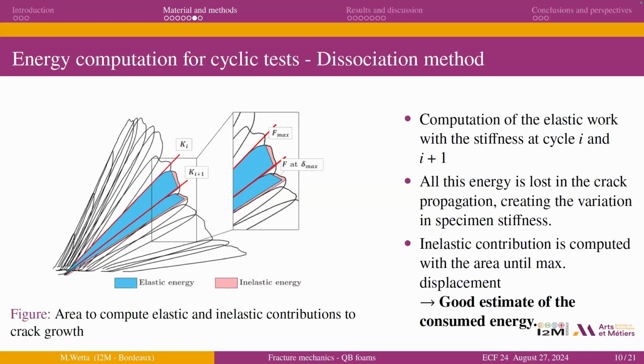To do that, we dissociate the blue and the red area. The blue is considered to be the elastic energy, which is estimated between two different stiffnesses, because when you reload the crack, you have a good estimate of the elastic stiffness. So between these two different stiffnesses at each step, it is possible to have a good estimate of the elastic energy consumed by the crack during its propagation. And the other contribution, which is the inelastic contribution, is obtained with the maximum displacement. And it is the red area just presented here.